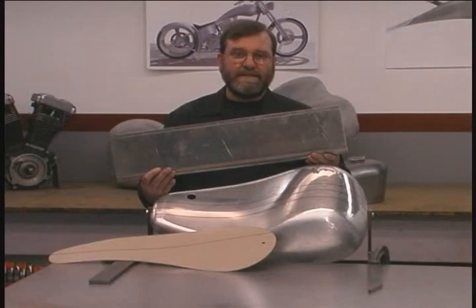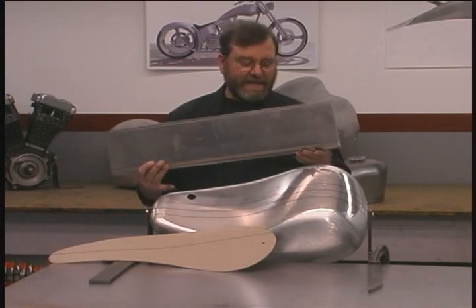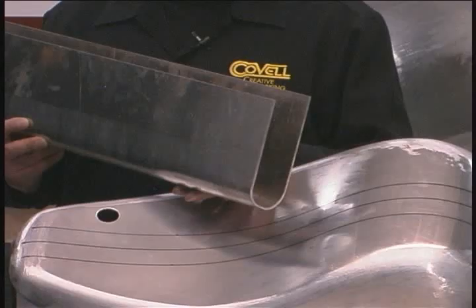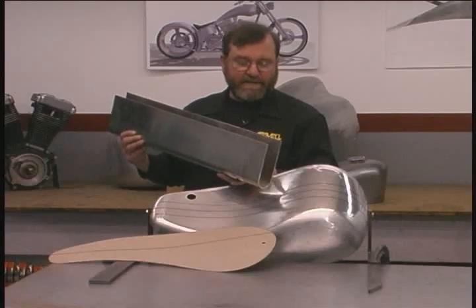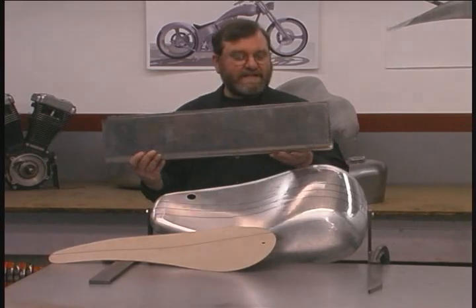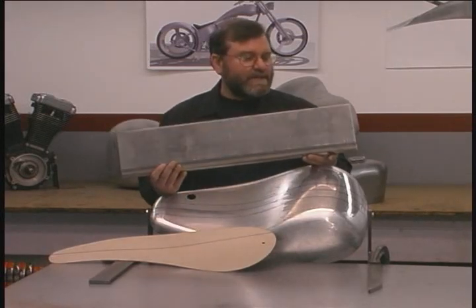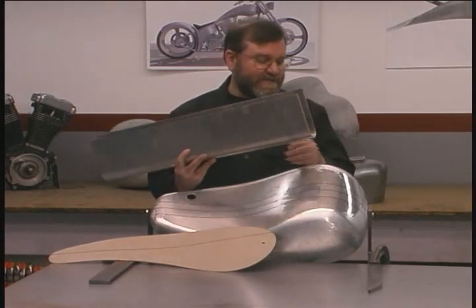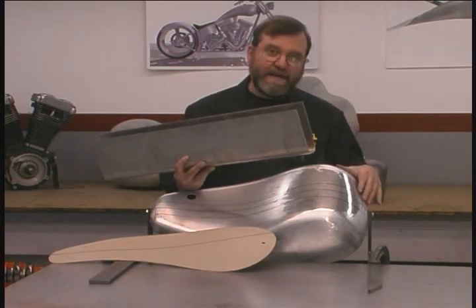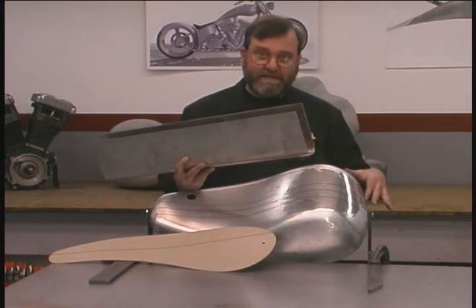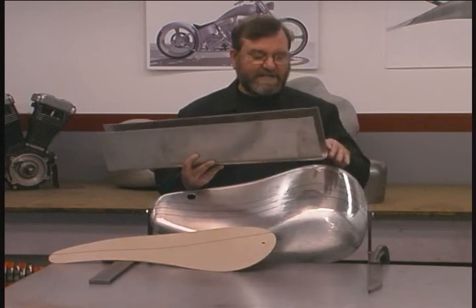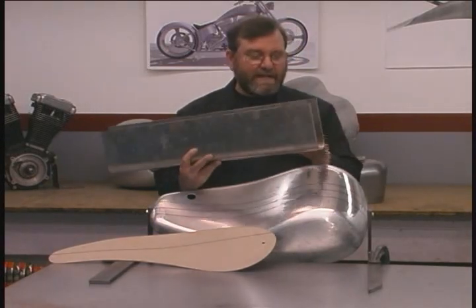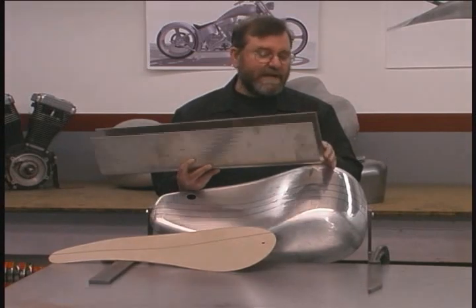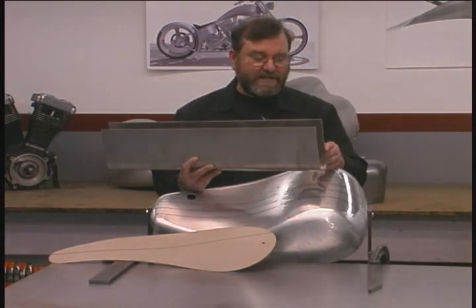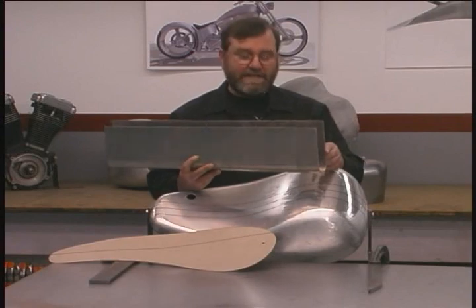We're going to fit the tunnel into the tank next. I've had this tunnel made out of especially thick aluminum. This is 1/8-inch thick aluminum. I've had it formed on a press brake with a radius die. And there's a very good reason why I choose to use metal this thick for the tunnel. Aluminum tanks are famous for cracking, and most often they crack at the area where a heavy mount is welded onto the thin skin of the tank. So my strategy is that by putting a very heavy tunnel in a tank, this becomes a backbone, essentially, that we can weld tabs onto, and that should make a very strong tank that should live a long time.